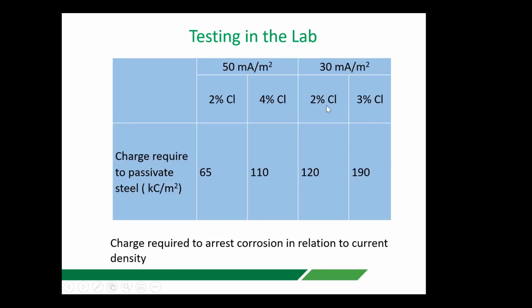So it was easier to passivate if you applied a higher current density. But of course, 50 milliamps per meter squared tends to get the cathodic protection engineers slightly nervous, because it's considerably above the 20 milliamps per meter squared that appears to be allowed in the standards. So we tended to focus more on the 30 milliamps per meter squared. And if it's over a short period, then that tends to be more acceptable.